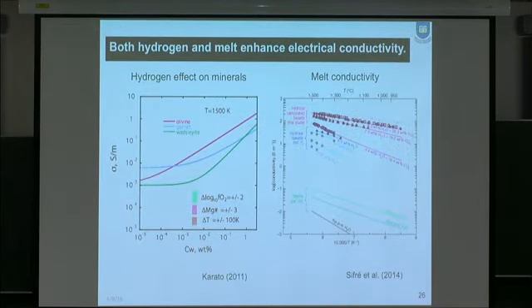There are two possibilities, as I mentioned. Hydrogen enhanced conductivity, as has been shown in my laboratory for the last 10 years. The hydrogen effect is quite enormous. If you go from dry to a pretty water-rich environment, conductivity can change by a factor of 100. But melts also have, in general, much higher conductivity than minerals. So therefore, the presence of melt may also be the cause of the high conductivity.